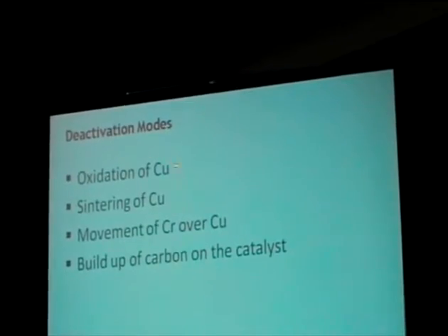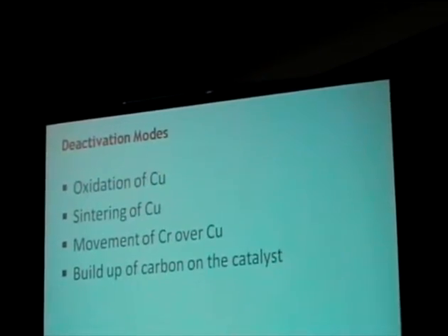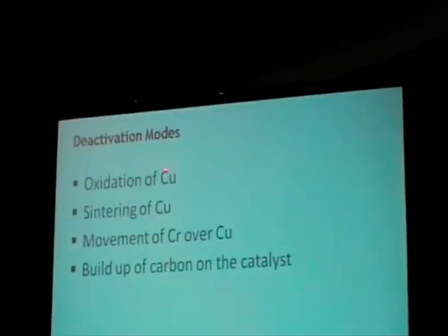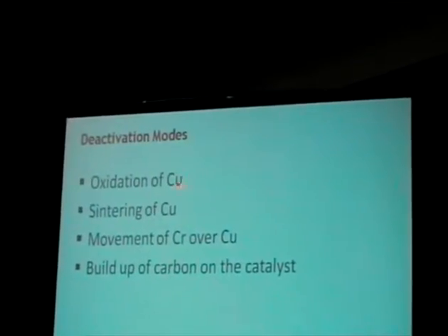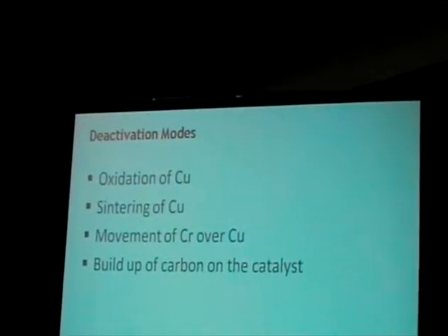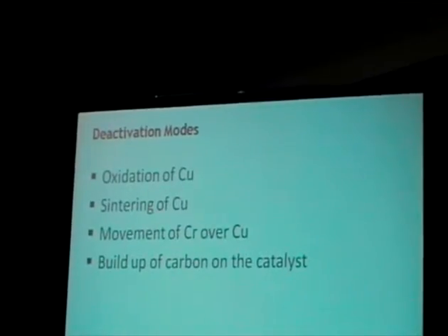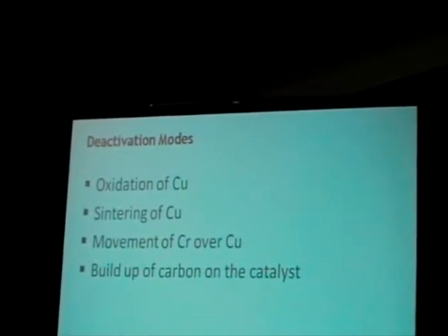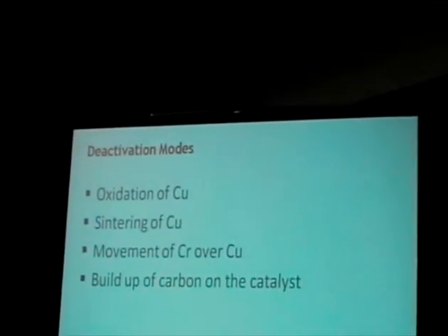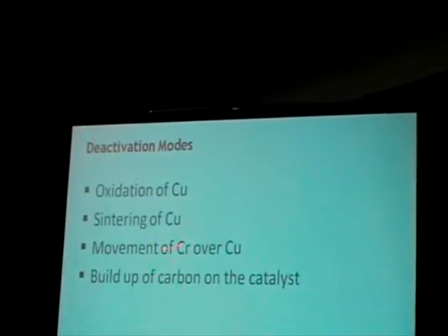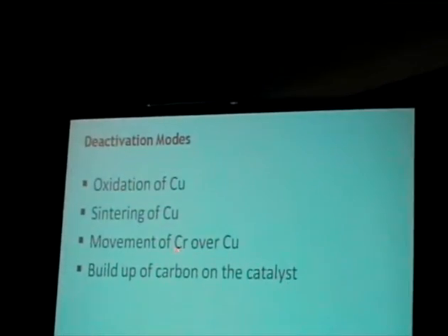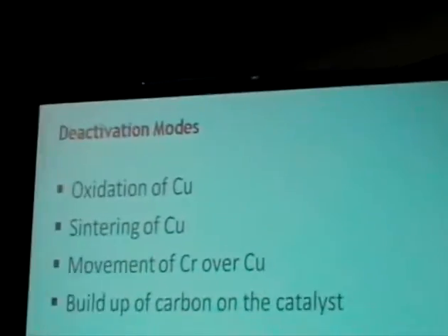It's believed by some papers that copper 1 is the active component, and it's oxidized to copper 2 in the reactions. Sintering of copper has also been listed. There's some literature that states that chromium is moving over the top of copper. And then finally, of course, buildup of carbon on the catalyst has also been implicated as a source.